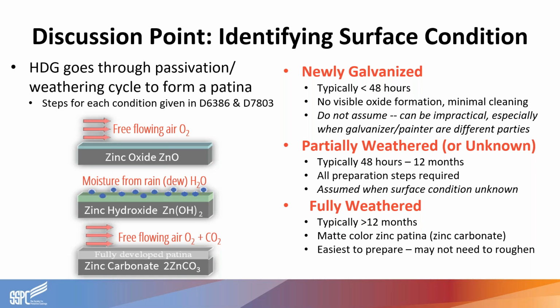There's going to be zinc oxides and zinc hydroxides very likely to be present in that time period, and these will need to be removed before the parts can be successfully painted. This is what's known as a partially weathered surface, once a galvanized surface has started to allow surface oxidation to occur. And it's the most common surface condition that the coating applicator is going to run into.